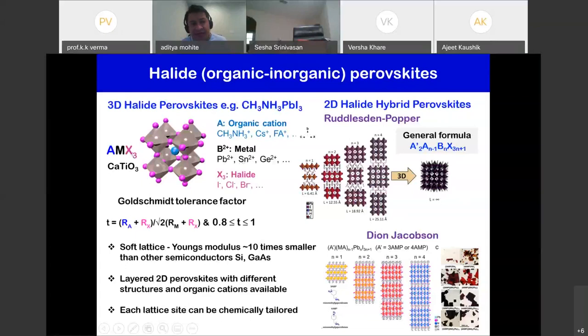And then the X here was the halide, which was basically iodine, chlorine, bromine. And so if you replace this with any of these compounds or combinations of them, and you work out something known as the Goldschmidt tolerance factor, which is given by this formula here, which is just a ratio of some ionic radii, if you get a value between 0.8 and 1, it means that you made a perovskite material. Okay. And so that's what it is.